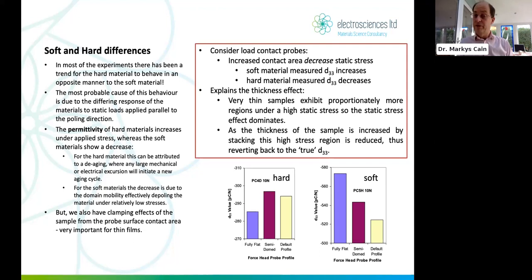Very thin samples exhibit proportionally more regions under a high static stress. Okay, so when you have a very thin sample, like a thin film or a thick film, or a very thin, like 0.5 millimeter thick ceramic piece, then the region of that material which is experiencing a high stress and therefore possibly high depolarizing stresses is increasing as a proportion of the total volume of material. So we might see a real impact of that when we measure the property of that material with different stresses.